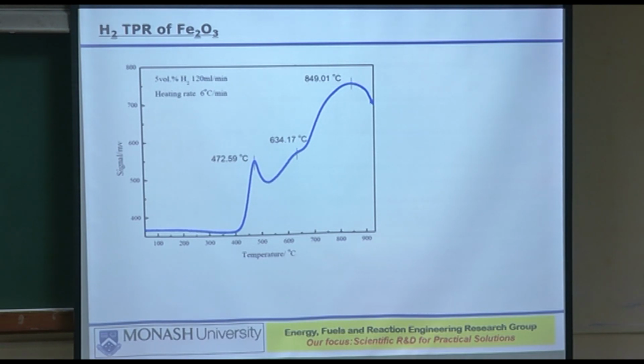The interesting point is, this is hematite, it's TPR reduction. Up to that sort of temperature, nothing happens. Then here it starts to happen, and there is a sharp peak at about 472.59 as measured by the thermocouple inside the TPR instrument. TPR is used extensively by the catalyst research community. We used it for different purposes. Here you are seeing that it starts to reduce in the presence of hydrogen at 473. In the synchrotron, we saw it around 550. Between these two, you can get a feel for where exactly things happen.